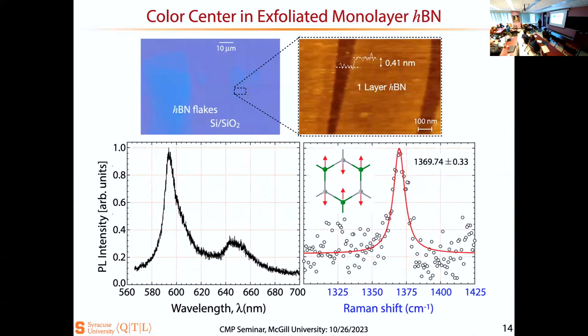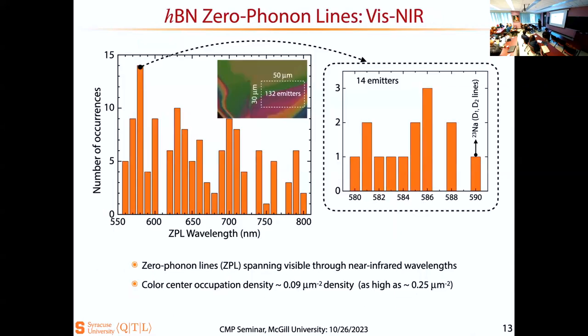Let me call it the local dielectric environment, otherwise known as junk sitting on the surface. Yes, it can shift. If it is stable enough, I would say it can lead to a shift in the zero phonon lines.